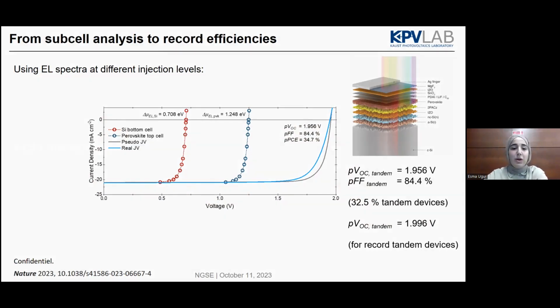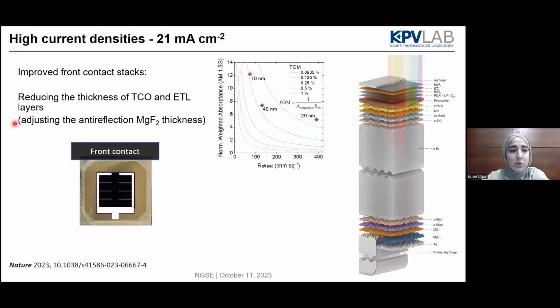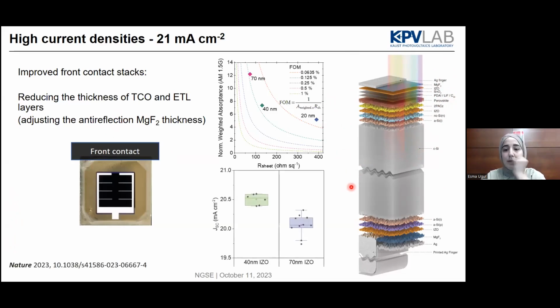And after that, maybe I want to show a really short explanation of how we are getting the higher current density. This was just recently put online, actually it's in an accelerated publication. Maybe within 2 weeks, let's say. So what we were doing, basically, is that first we focus on the top part of our tandem device, and we reduce the thickness of the TCO that we are using, and also the other stack. So you can see here that we went down to 40 nanometer, we reduced the top TCO.